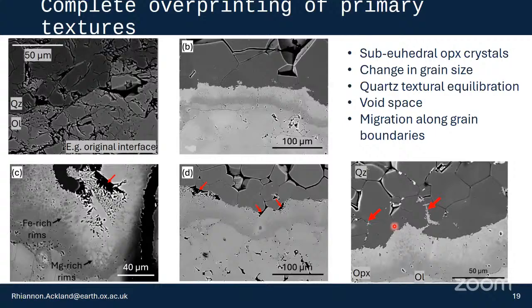So this tells us one of the first key findings about these replacive textures: there's a complete overprinting of the primary textures. If you have this original interface with olivine and quartz adjacent, the orthopyroxene is completely overprinting this, it's not inheriting the original crystal structure. We have subhedral to euhedral OPX crystals developing. We also have a change in grain size.